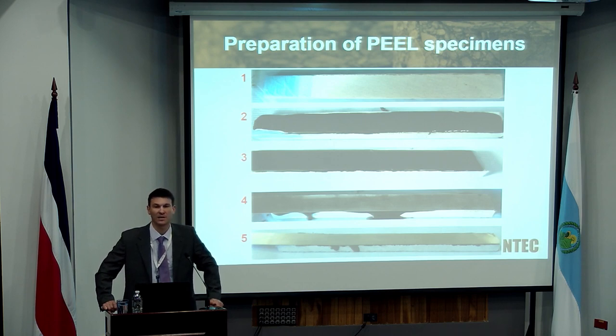So the copper wire has a very, very well-defined thickness. This will be standard gauge copper wire. We could change the thickness from 100 microns to 150 microns to 200 microns, depending on what we were looking at. But using those almost as gauges, we can very accurately define the thickness of our adhesive layer. Once you've done that, you very carefully place your peel arm. And your peel arm, as I mentioned earlier on, will be some form of aluminium strip. And we can play around with the dimensions and the thickness of that strip, and I'll show you some examples of results we get in a second.